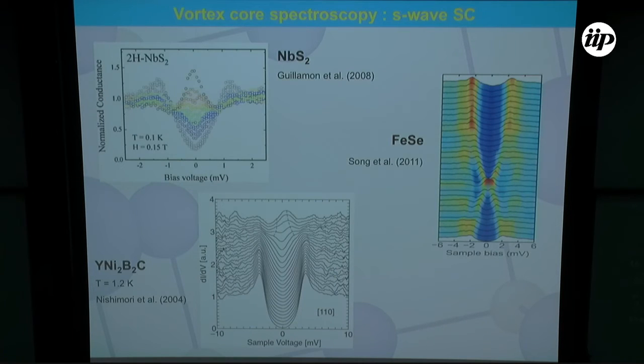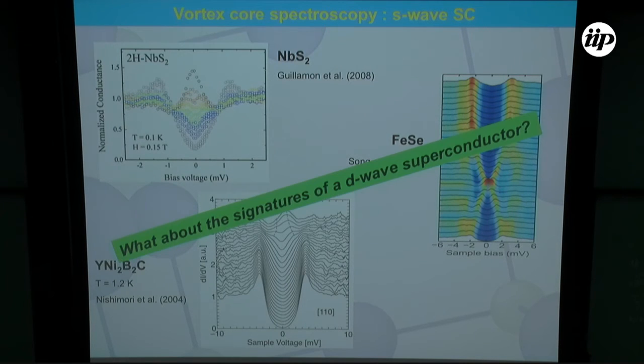And this has then been measured on a variety of compounds, S-wave superconductors, dichalcogenides, iron selenide, or borocarbide compounds, where in all cases you see that the center of the core shows a zero bias anomaly and a split while going from the inside to the outside. Okay, so far so good, but what about a D-wave superconductor?